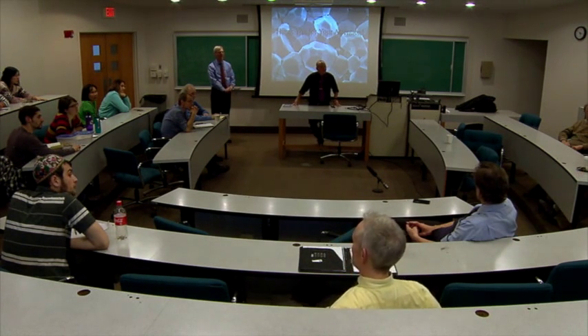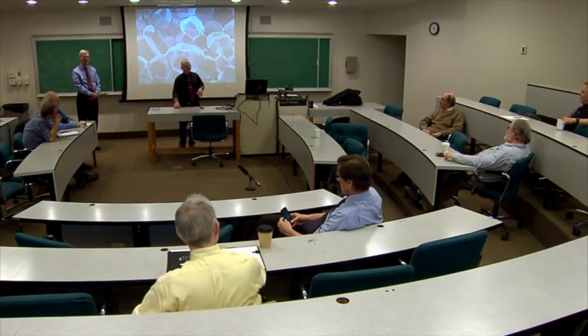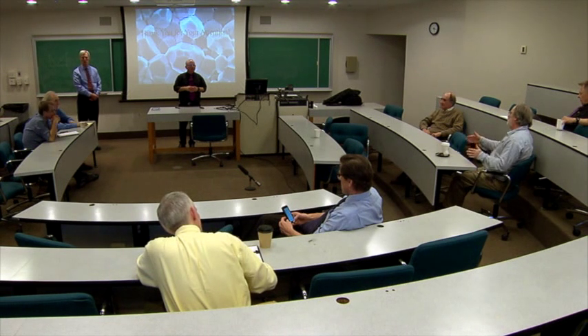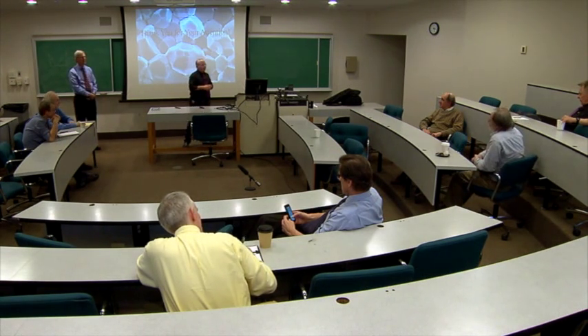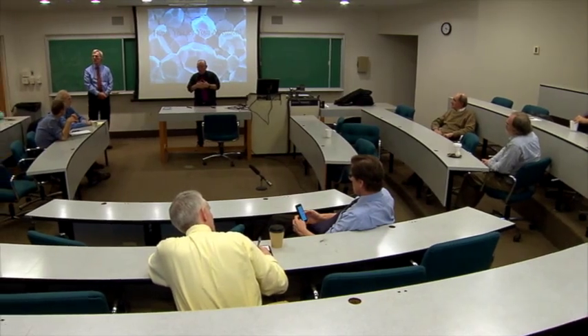Peter, so the accelerated grain growth in alumina, are they going to be linear as symmetric, or is it plates that you just intersect? They're plates. In this case with the calcium, they're plates. They're not whiskers, they're flat plates. What about the growth in the various prismatic directions, are they about the same? I don't really know. I think they're about the same. I haven't measured them. So they only slow down on the basal.